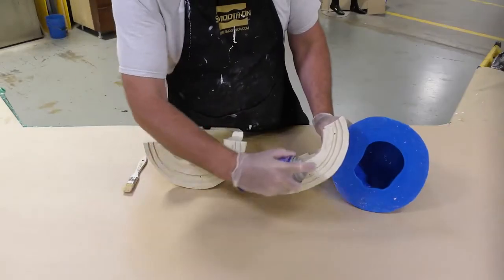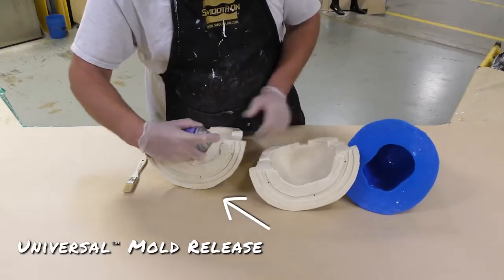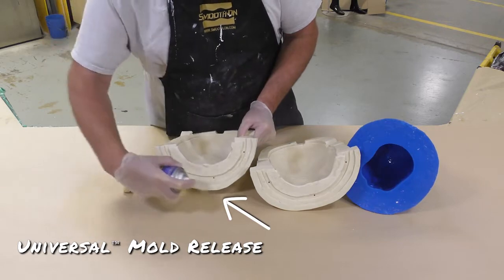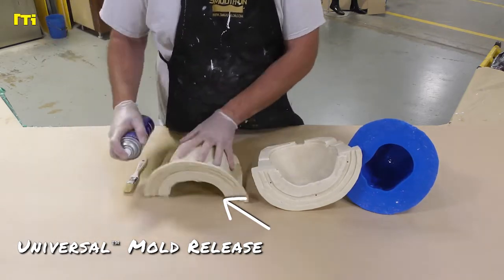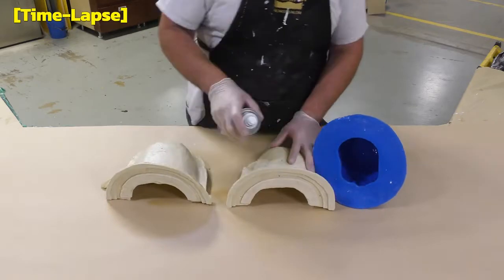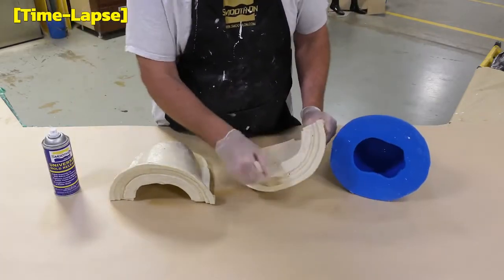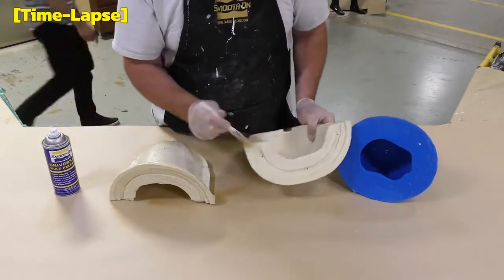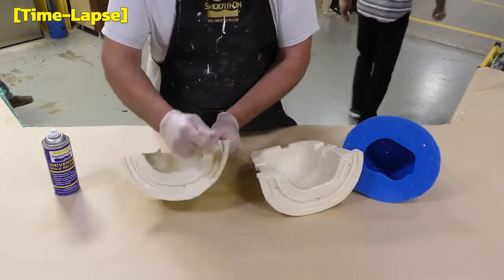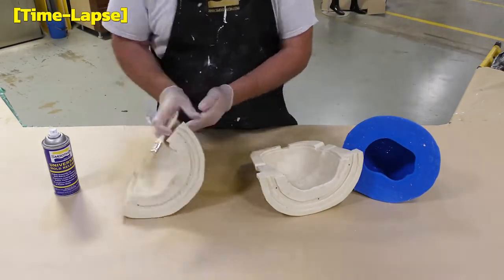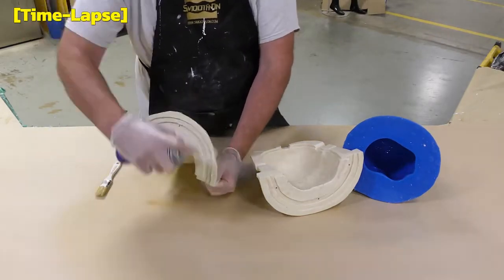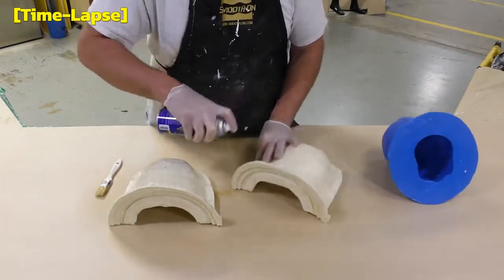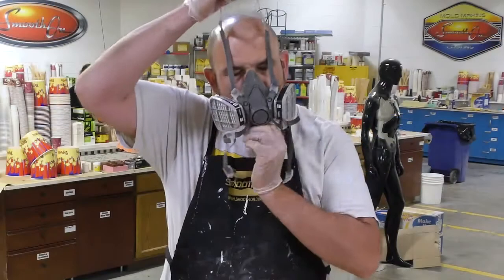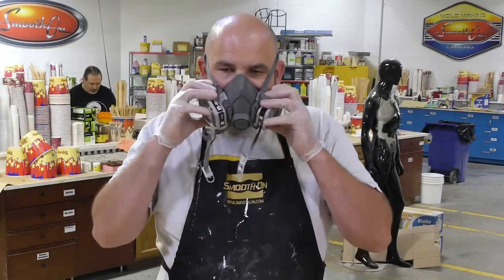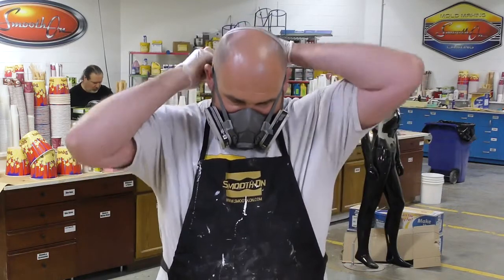Now, I'm planning to do a rotational casting, and as such, I'm already anticipating spilling some of that material out of the mold. I don't want the crystal clear, which is a urethane resin, to stick to our support shell, which is also made out of a urethane resin. So for that, we're going to apply some universal release agent to the support shell to minimize any possibility of the resin sticking to our support shell. Also, the proper respirator is now applied before dispensing any of the material.